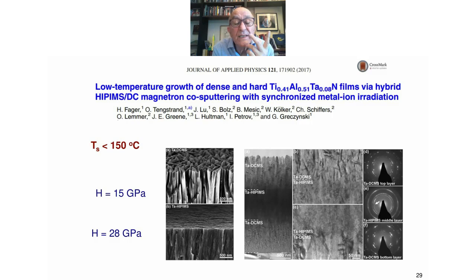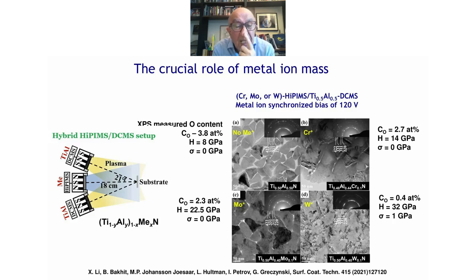Similar results with titanium aluminum nitride and tantalum. You can see again densification with significant increase in hardness. Next one. Now, we studied more systematically the role of the metal ion mass. And here we have these two titanium aluminum targets sputtered in DC. In the middle, we changed the metal from group 6B, the ones that we can select as the metal component by synchronized bias.